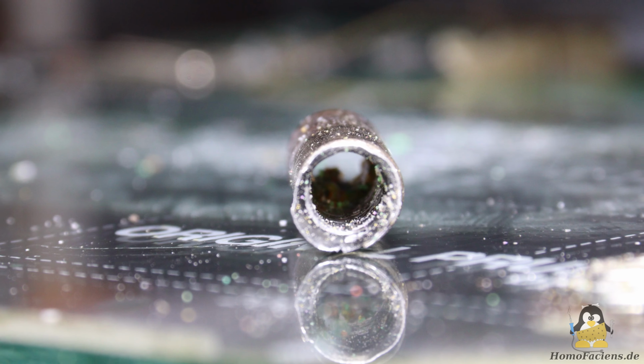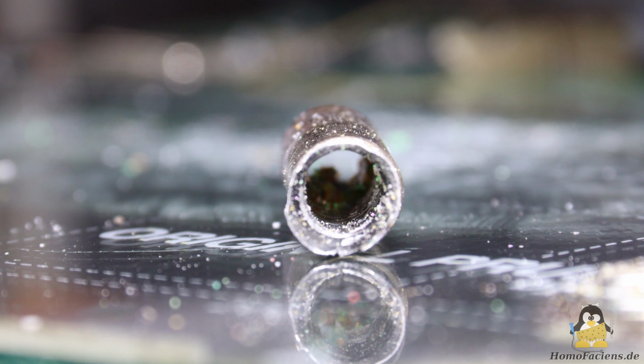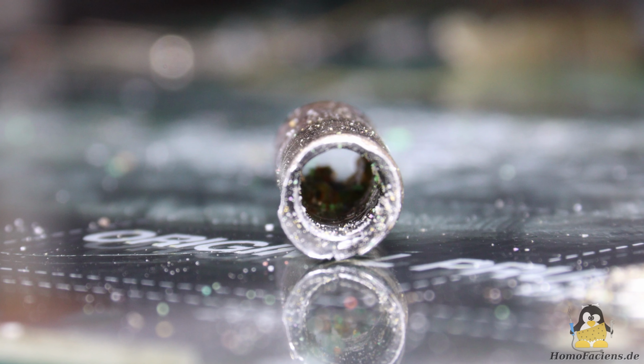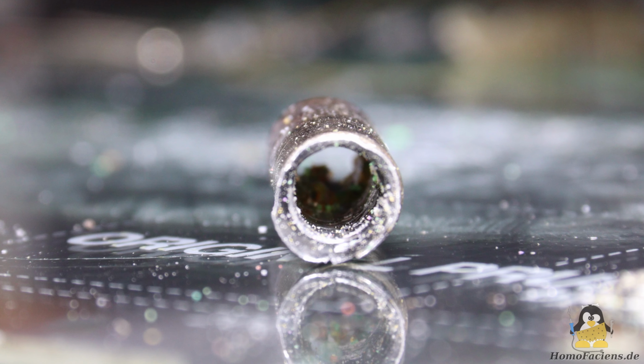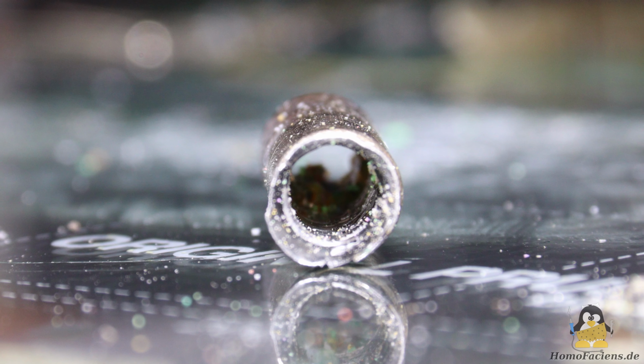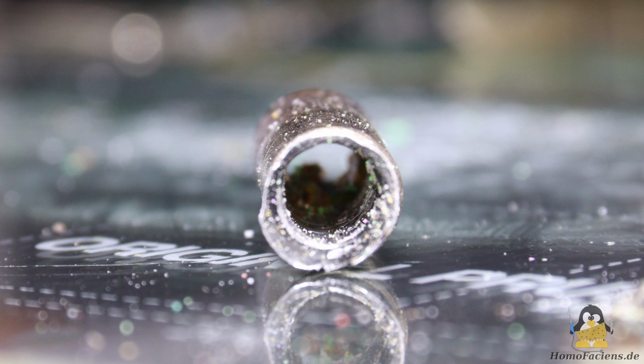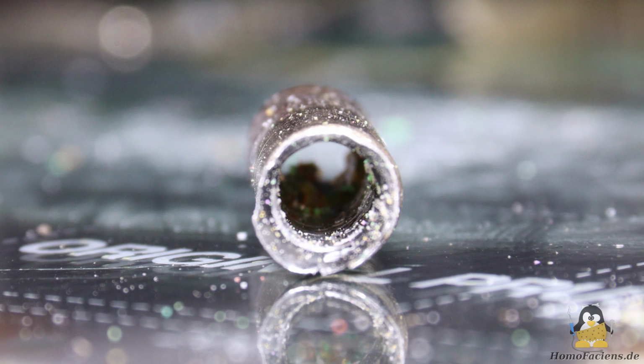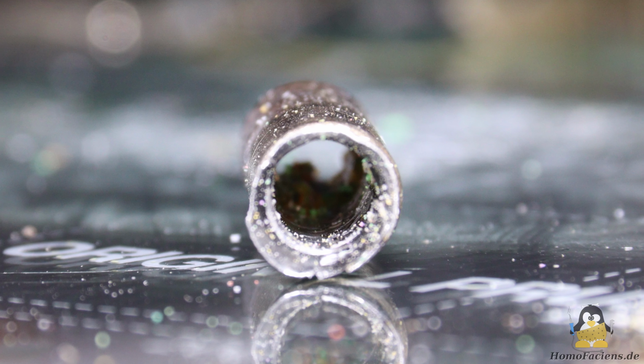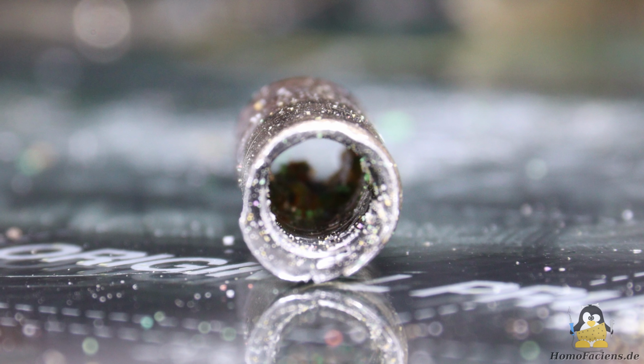The resulting idea greatly simplifies the extruder design. The tube now consists of a smooth walled tube, as in the initial experiments. A simple trick prevents the plastic from sticking to the screw and subsequently rotating with it in the melting zone.